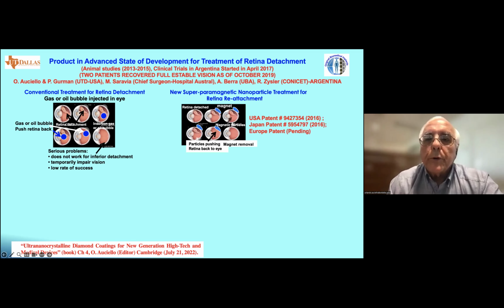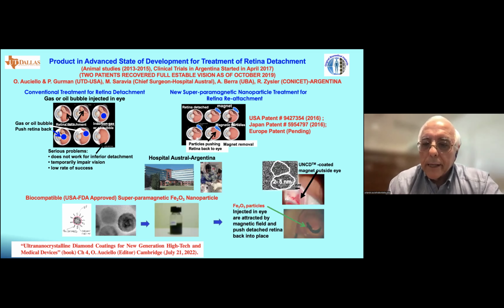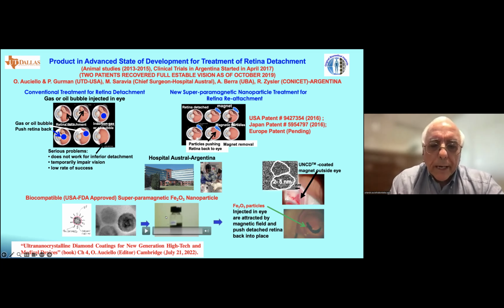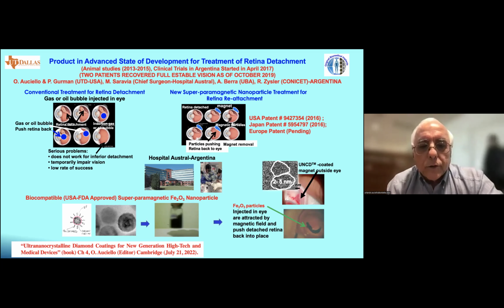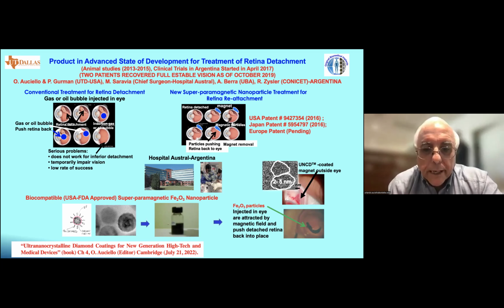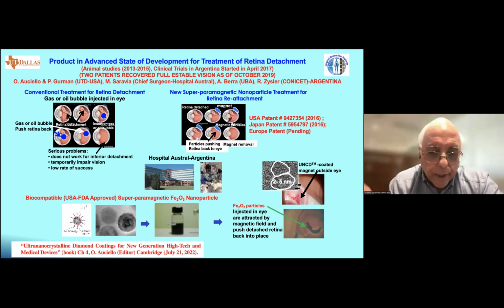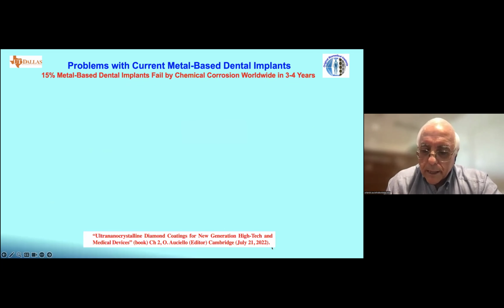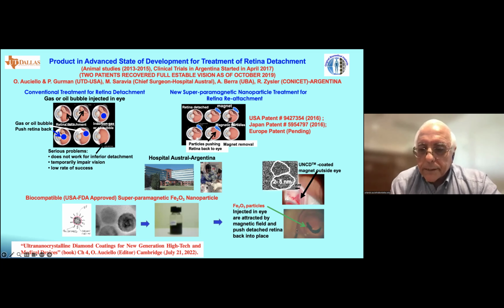So what we developed is a new process where we put a UNCD-coated magnet outside the eye, as indicated in here. We inject superparamagnetic nanoparticles that are iron-2, oxygen-3. Fortunately, these particles are approved by the FDA in the United States for other treatments, and they become magnetic only when they see a magnetic field. So what happened here in the laboratory happened in the eye here. The particles are attracted, push the retina. After 10 days, the retina is attached. We take the magnet out, the particles dissolve.